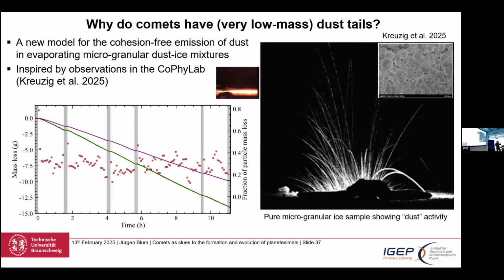So we shine light on it. It throws out, it evaporates, of course, because it absorbs in the infrared some of the energy, but it throws out particles as well. And the fraction of particles thrown out, the dots here, is on the order of 20 to 40%. So 20 to 40% of the mass that we're losing here goes out into solid particles, and the rest, 60 to 80%, goes out as evaporation, as we had anticipated. And we had to understand that. Where does that come from?